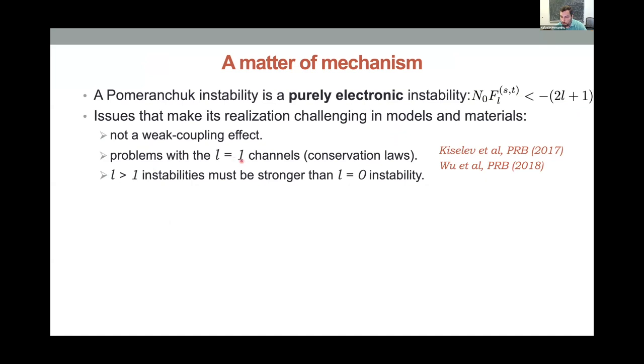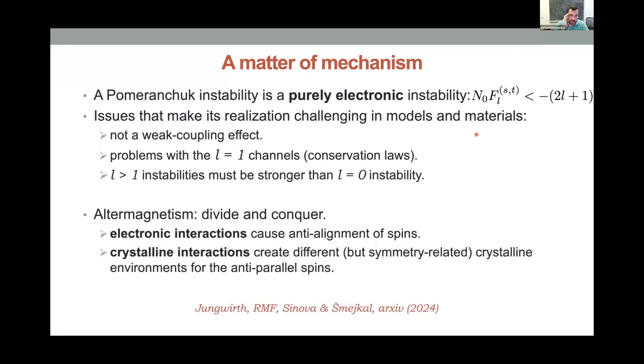There are issues with the L equals 1 channels because of conservation laws, and this has been widely discussed in more recent papers. And for the L larger than 1 instabilities, including what would be equivalent to the altermagnet, the main issue of finding microscopic models or materials is how you can ensure not only that the interactions overcome this threshold, but that this happens without all the other angular momentum channels, including L equals 0, happening at the same time. So it's been very elusive to find these states in models, especially the spin triplet ones. And what altermagnetism does, that's one point we cover in this review, is it essentially divides the problem in two.